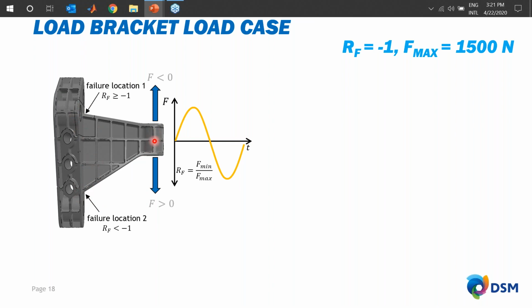So if you go to R = -2, which means that you push twice as hard as you pull in the maximum load, then you see a failure location here on the bottom. But for all the other ones, where the R value is bigger than -1, that means that you pull harder than you push, then you always see failure on the top. And this was also correctly identified by the framework.